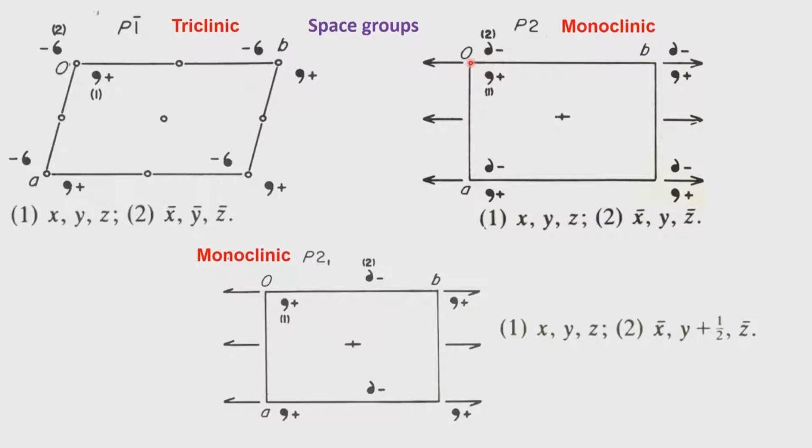This comes at an angle of beta, and that therefore qualifies this complete description of this space group P2. The addition of a half translation is invoked in the case of a 2-1 screw axis. So, instead of a two-fold axis, if we have a 2-1 screw axis, then you see the operations very clearly: x, y, z will now undergo a two-fold operation, and after the two-fold operation you will see there is a half translation along the direction of rotation.